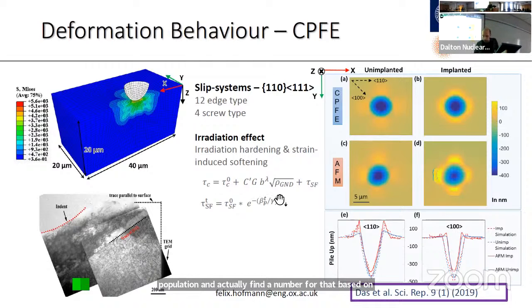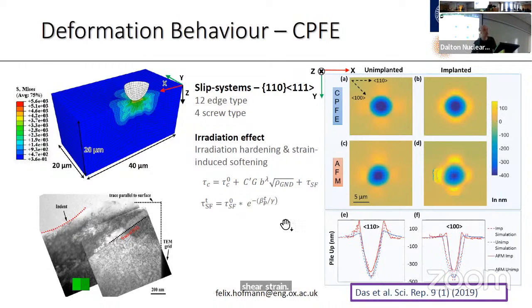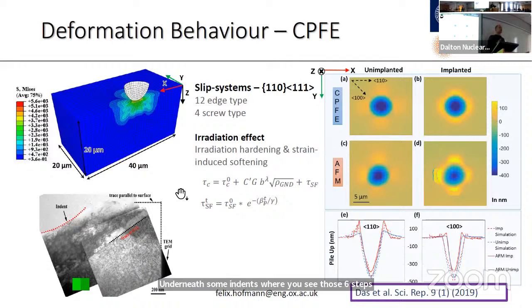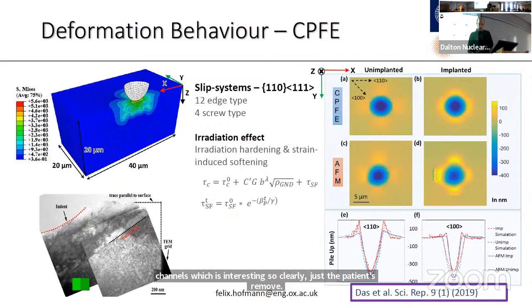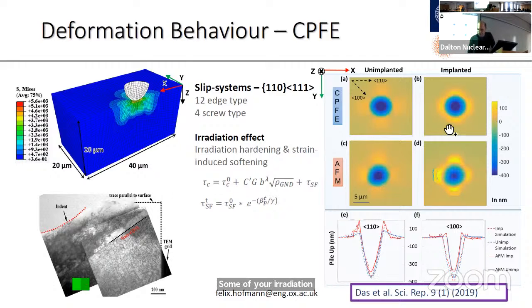And then there's a little bit of a fudge factor here, which is that as your plasticity progresses, gamma here is the accumulated shear strain. As the shear strain increases, you have some kind of softening. And that's justified because when we looked in the TEM underneath some indents, where you see those slip steps, you effectively have channels that appear to have been cleared out of irradiation defects. So you have these almost perfect material channels, which is quite interesting. So clearly the dislocations remove some of your irradiation-induced obstacles.